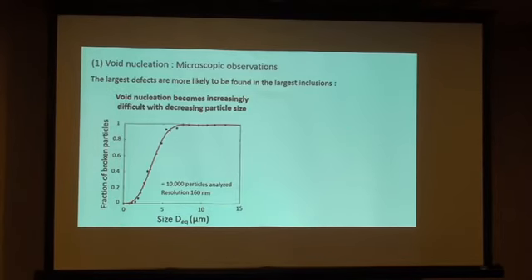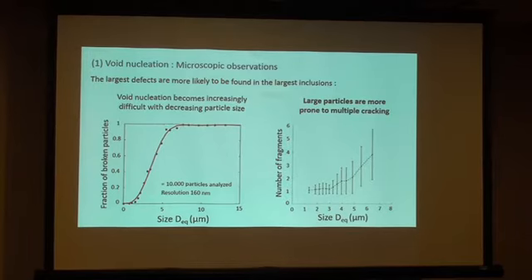And doing this, we can look at the fraction of broken particles as a function of the size of the particles. And you see that, as I said, there is a huge size effect. For the big particles, you've got a lot of chance to find a micro defect, and they are almost always broken, and the opposite for very small particles. Also, if you look at the number of fragments as a function of the size of the particles, you see that as the size of the particles increases, the number of fragments, so the number of broken pieces, also increases, which is quite intuitive.